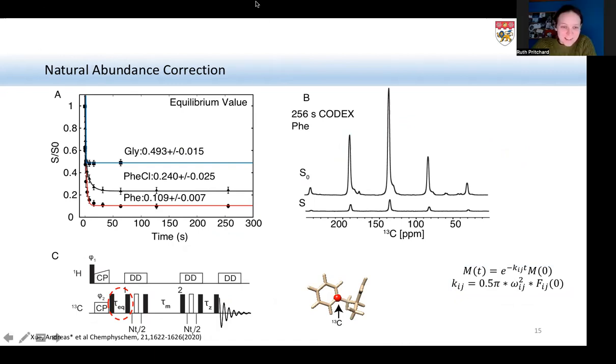It's really interesting. What we show here is that for glycine, our curve decays to half, and for phenylalanine hydrochloride, it decays to approximately 0.24. But for the phenylalanine dissolved in water and crystallized at neutral pH, which from the crystal study we know should be decaying to 1/8, the Z prime value is 8, but we observe something closer to 0.109.